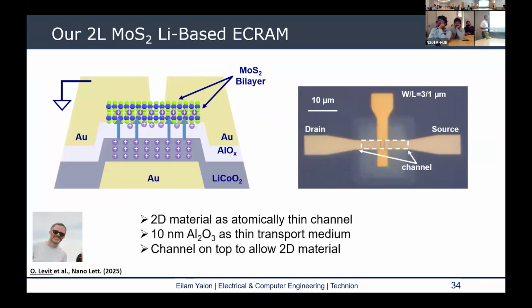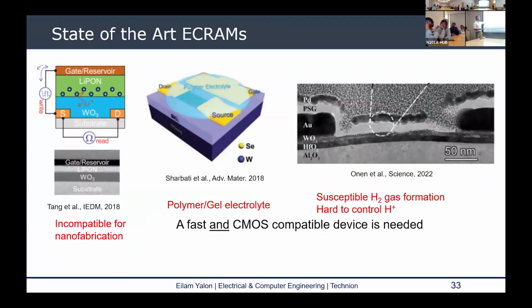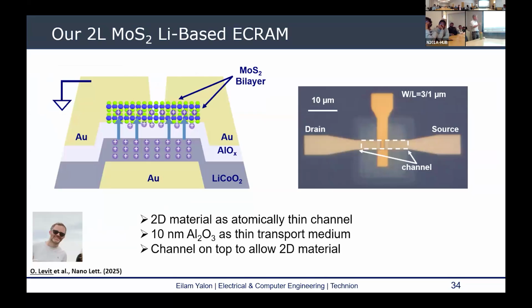So our proposal is to use a 2D material as the channel transistor for several reasons. One of the reasons is that it's atomically thin, so there is no redistribution of these mobile ions within the thickness of the channel. The other is that it's a crystalline material, which has certain advantages over the previously used amorphous oxides like tungsten oxide, which most works use as a heavily degenerate material. So the 2D material is atomically thin and crystalline, and has some advantages. So we went ahead and fabricated.